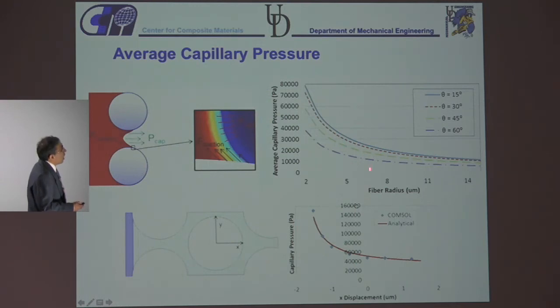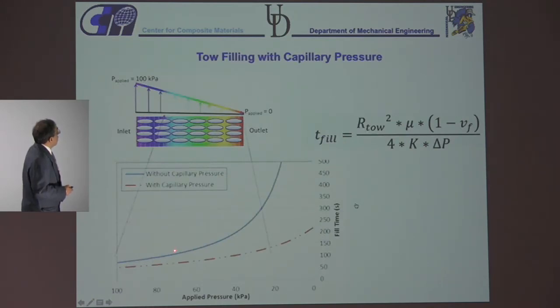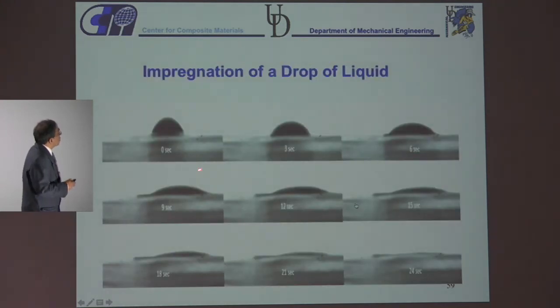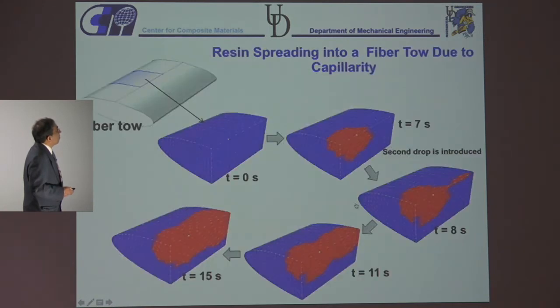And it also depends on the contact angle of the fluid. So if the contact angle is small, your capillary pressure is higher, and if it is high, then the capillary pressure is smaller. And as I said, it is important more near the flow front and not here, because the pressure is much higher here. And so that's where it is important. And as you can see, the effect of contact angle: you put a drop, it takes 24 seconds to go in. It may take longer if it was a less wetting fluid.